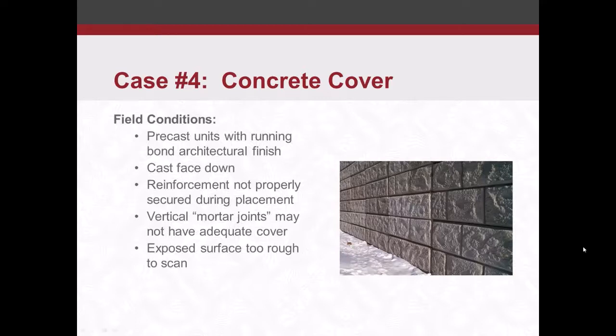And these vertical mortar joints, again, these are precast panels, so these aren't actual joints, they're just cast-in joints, right? But these vertical mortar joints may have had inadequate cover. So the bars cast closest to the surface were the horizontal bars, spanning across these vertical mortar joints. We use ground penetrating radar. We can get reinforcement coverage pretty good with ground penetrating radar, but the surface being so rough, we couldn't roll our GPR across the surface.